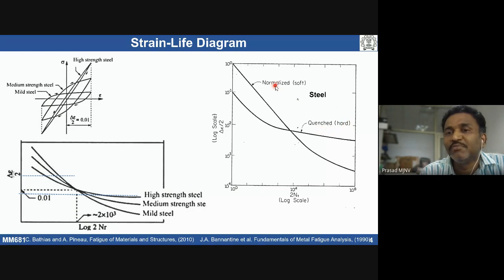Assume that I have a medium carbon steel. Within medium carbon steel, we can get pearlite plus ferrite. In the quenched one, we will get martensite, because martensitic steels are hard in nature as compared to normalized steel. So accordingly, we do see this in the high cycle fatigue regime. In a high cycle fatigue regime, hard materials behave better. The fatigue performance of hard materials is better than normalized soft materials.